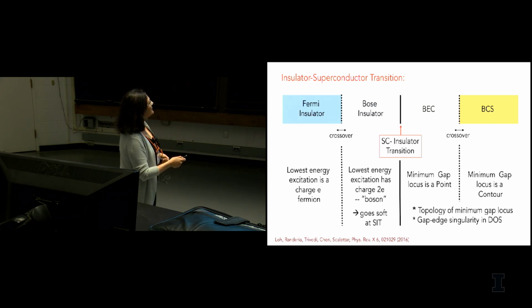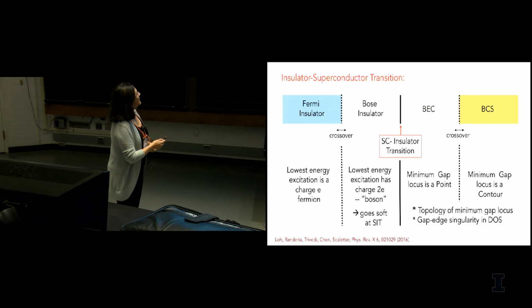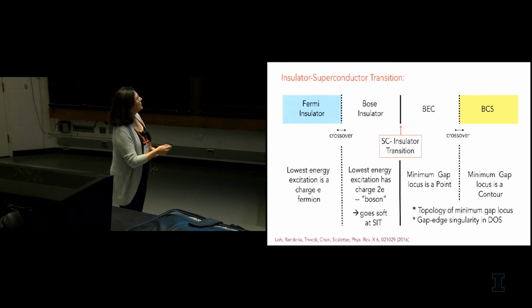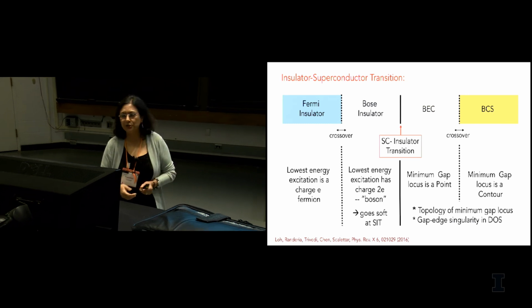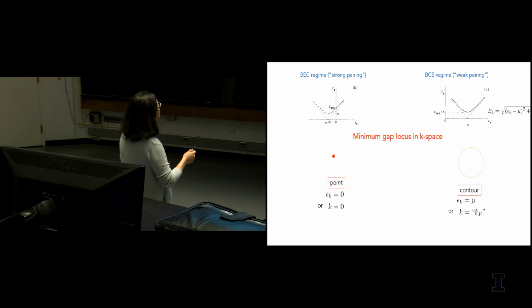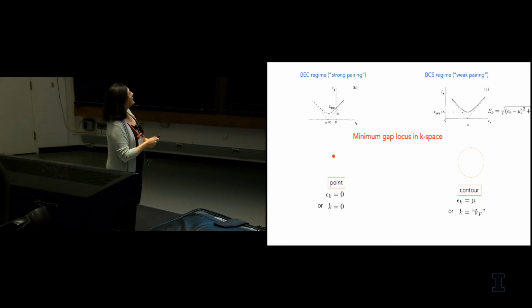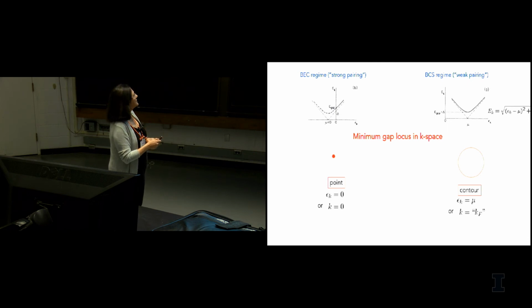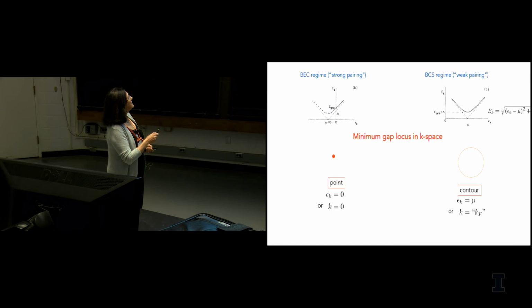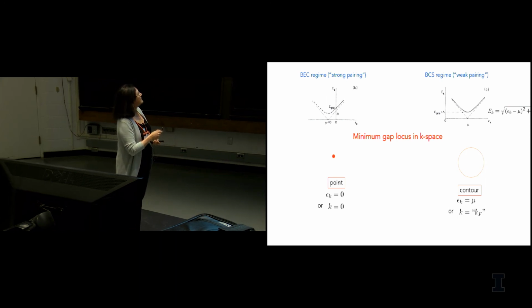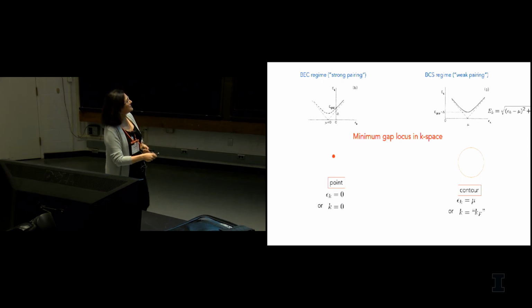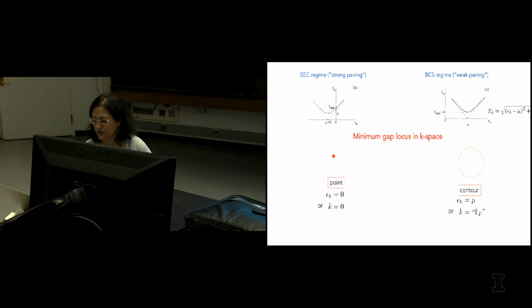It then goes into the superconducting state, but when it just enters the superconductor, it's a Bose-Einstein condensate. And then with further increase of the tunneling, it goes into a BCS superconductor. And the way we can distinguish these 2 is by looking at the location in momentum space where the minimum gap opens. So in a superconductor, in the BCS regime, if you follow the gap contour, it's essentially at KF, and you get a closed contour. Whereas in the BEC regime, the minimum gap occurs at the gamma point, so to say. So there's a change in topology of the minimum gap contour.